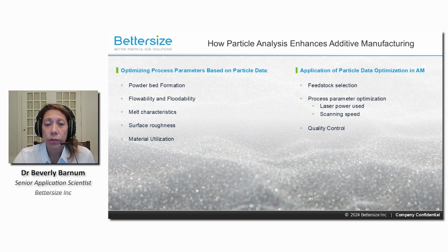Particle size and surface chemistry affect how particles melt and fuse together during the additive process. So these melt characteristics impact the final part's strength and density. Particle size and shape directly influence the surface texture of the final part, with smaller and more uniform particles generally leading to smoother surfaces. And by analyzing particle size distribution, manufacturers can minimize waste by optimizing powder usage and reducing the need for excess material.